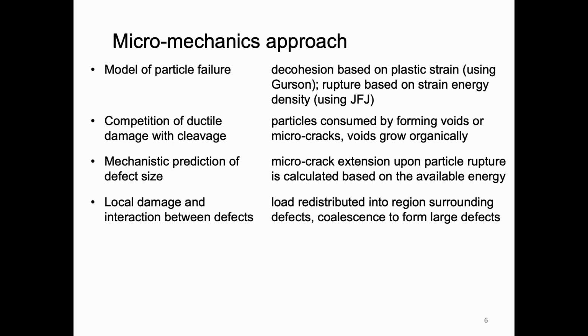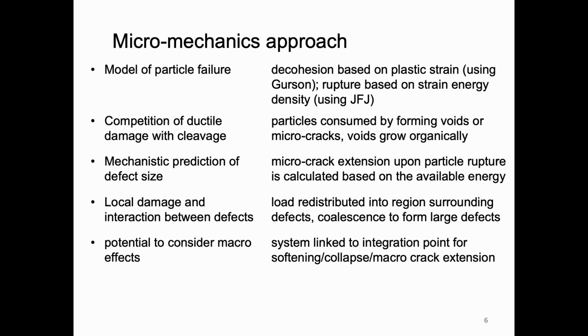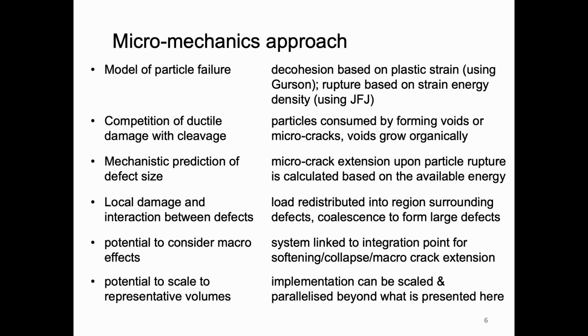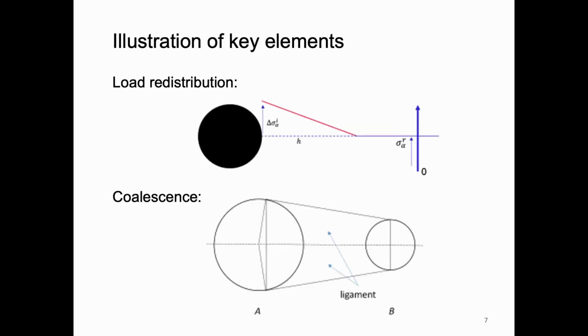to account for interaction between local damage between the defects, so that load is distributed into the region surrounding the defects that form, and the coalescence of defects. And eventually he wants to be able to consider macrocrack effects, so that he uses the model at each integration point separately, and then scales up to representative volumes. And I'm going to show only two simple things out of this, because it's a long story and you'll probably be able to read the details. But the load redistribution he handles in this way.